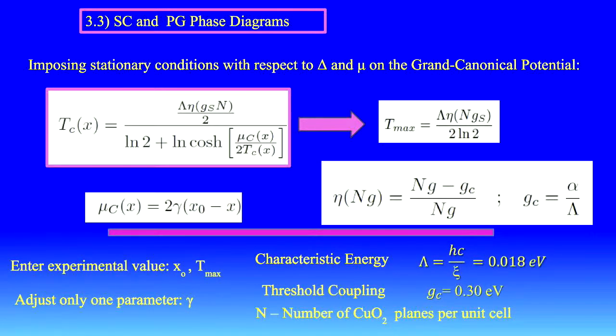So the superconducting and pseudo-gap diagram. When you use those stationary conditions, that the derivative should be zero with respect to delta and mu, we obtain this expression here for the TC. It's a function of the chemical potential and the temperature. Now, notice that this denominator is a monotonically increasing function of the chemical potential. So T max, the maximum temperature, so this is the dome.